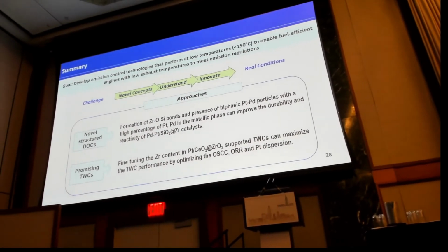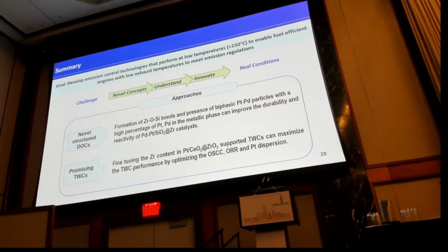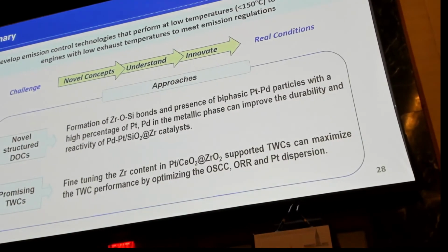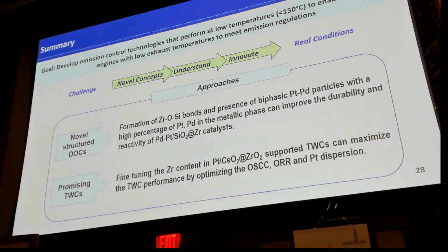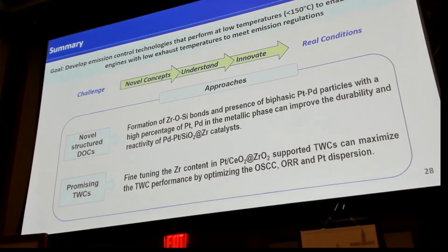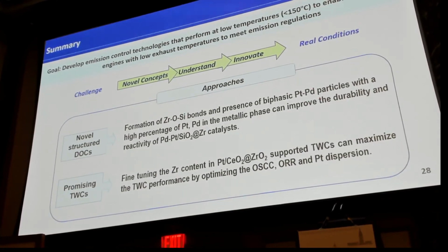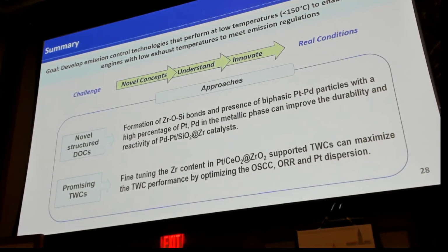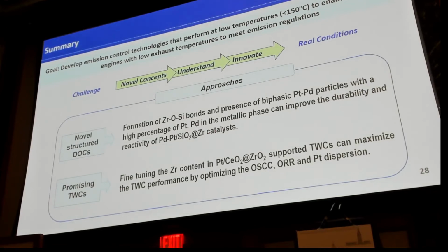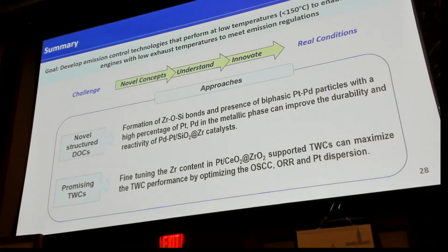So this summarizes my talk. I hope I convinced you that in the first part of my talk, on the silica and zirconium catalyst, we have formation of zirconium-oxygen-silicon bonds, and we have the presence of biphasic platinum-palladium particles with a high percentage of platinum-palladium in the metallic phase, and this can improve the durability and the performance of the bimetallic platinum-palladium supported on the silica and zirconium catalyst supports.